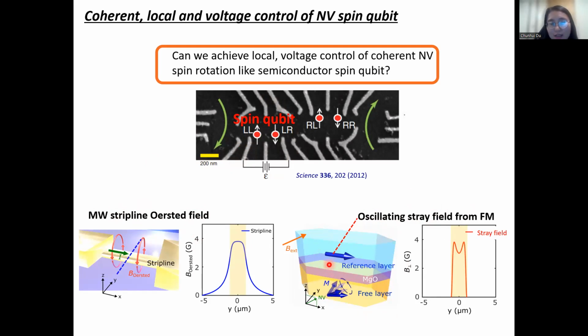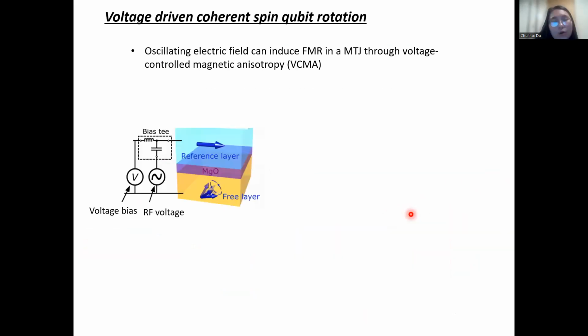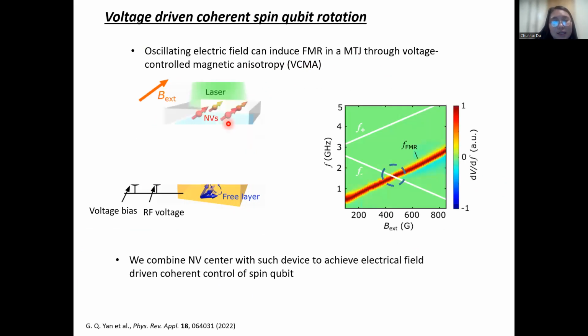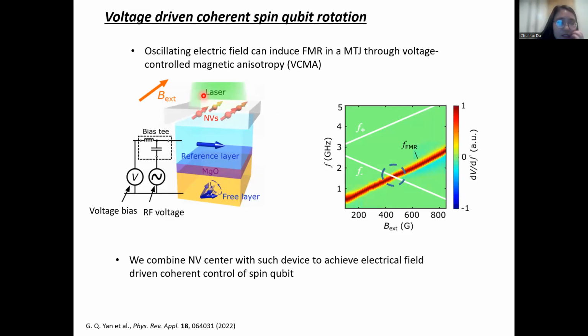So in this case, it's driving the NV center using the stray field, which decays much faster in space than the Oersted field. So this enables local control. And to enable voltage control, we can take advantage of the voltage controlled magnetic anisotropy in a magnetic tunnel junction. By applying radio frequency voltage across the junction, it can induce the variation of the anisotropy of the free layer, and this induces the resonance of the magnetization in the free layer, and this generates an oscillating stray field that can be used to coherently drive the NV center.